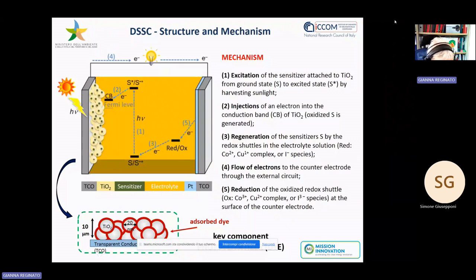In the presence of light, the sensitizer is excited, and that means that an electron jumps from the ground state level to an excited state, and if the energy of this electron is good enough, which means the energy of the excited electron is higher than the conductive band of titania, this can be injected into the titania and then, going through an external circuit, go to the other electrode where, using an electrolyte as carrier, it can be reduced and close the cycle.